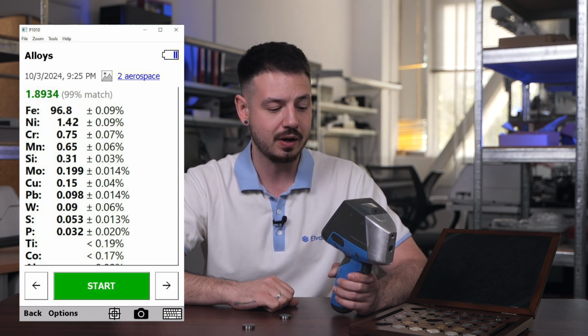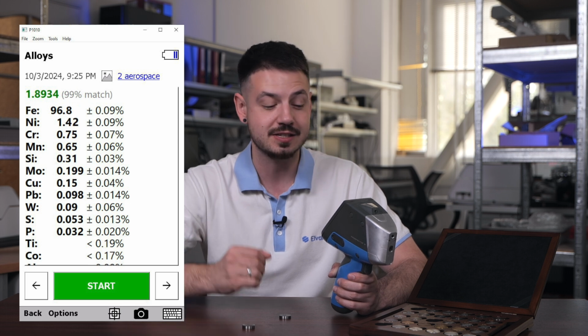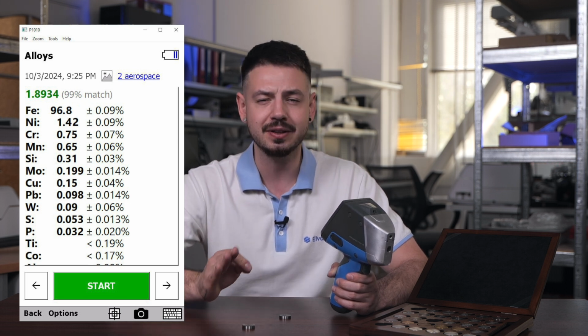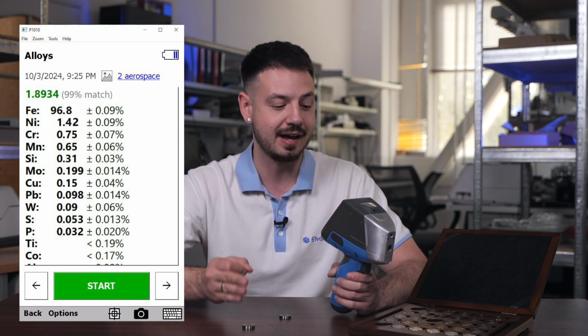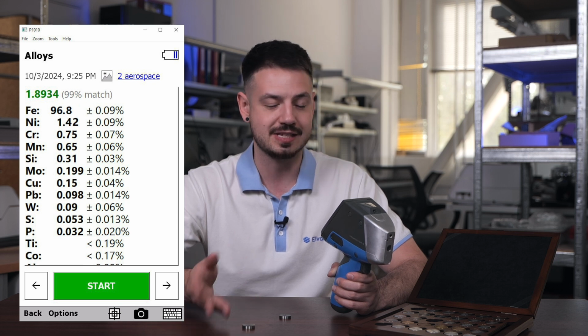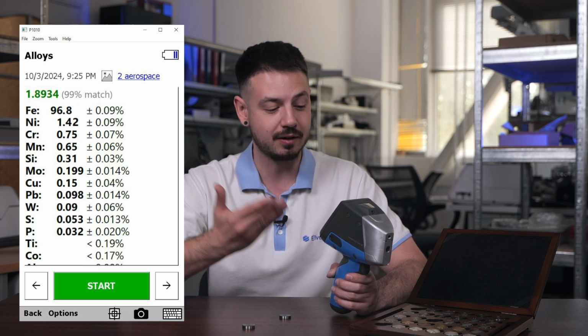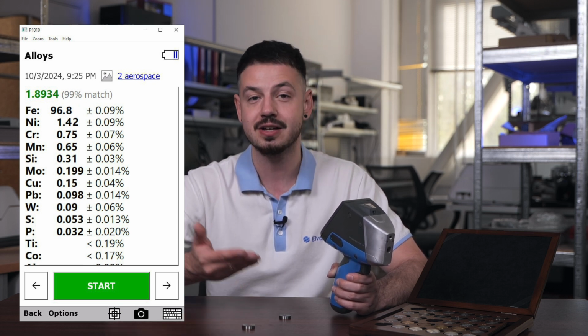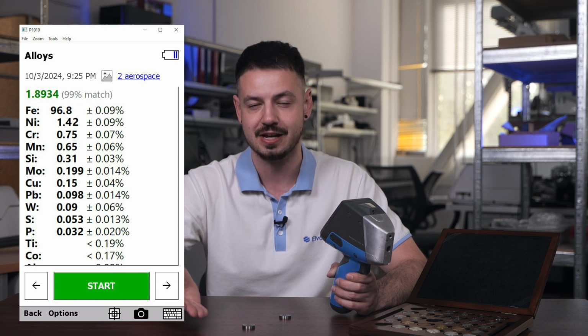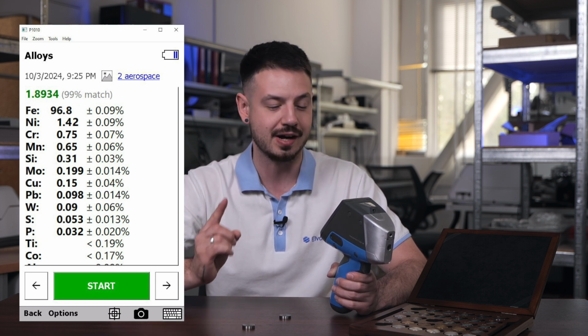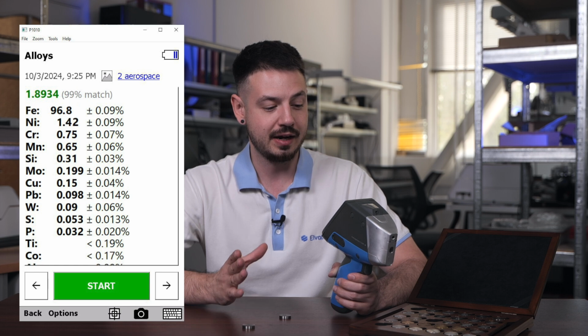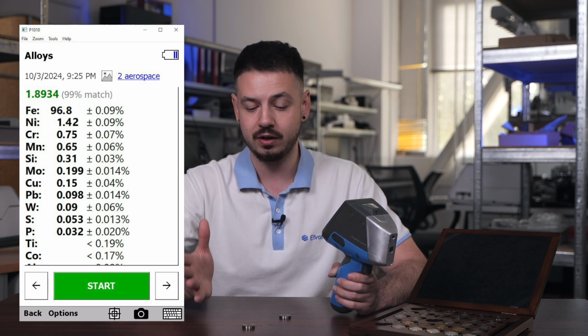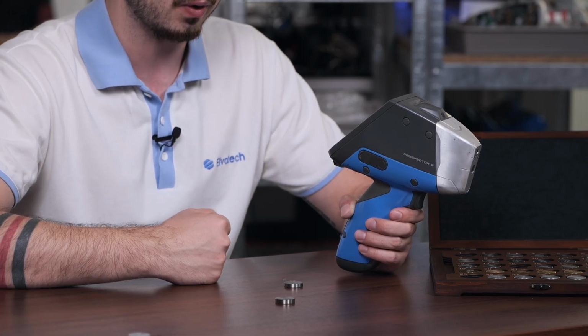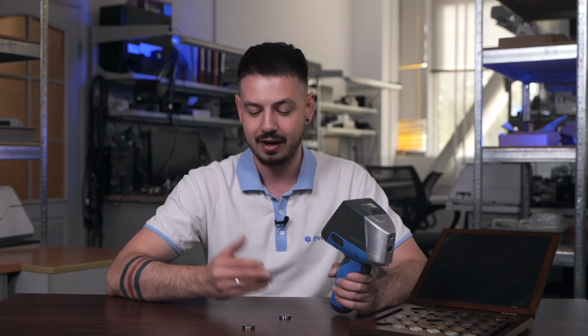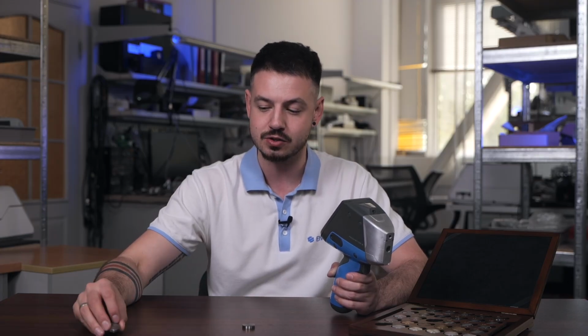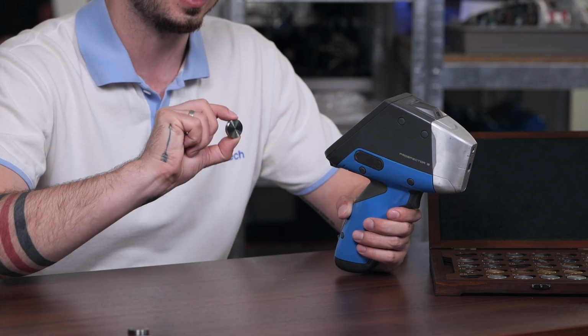And also we got chromium, at a little bit lower than just 1. It has 0.75, and the appropriate data for this sample is 0.76, so we are really close to 100% almost. Alright, we are done with the second one, and let's move on to our titanium aluminum sample, and it will be really interesting to see the contamination of elements in this one.